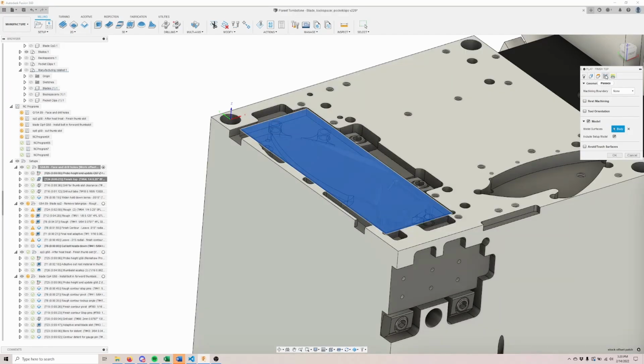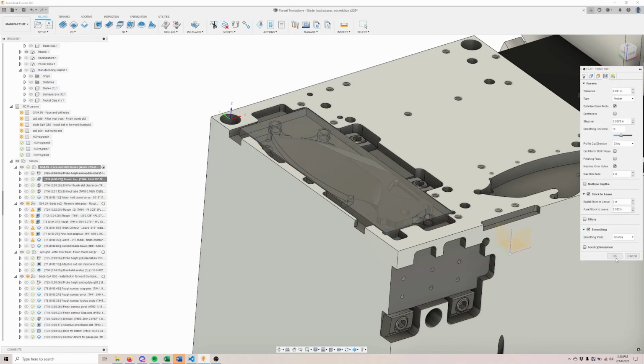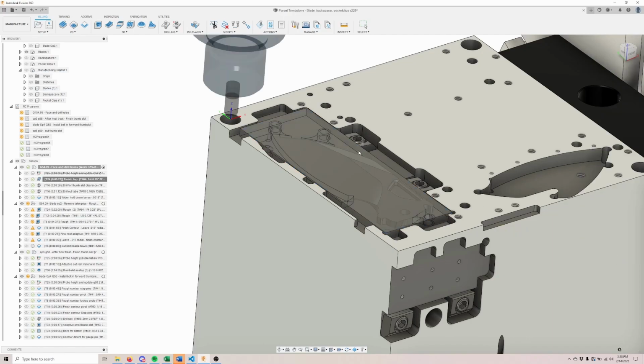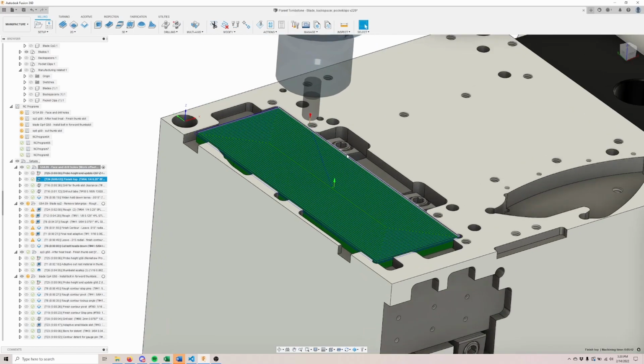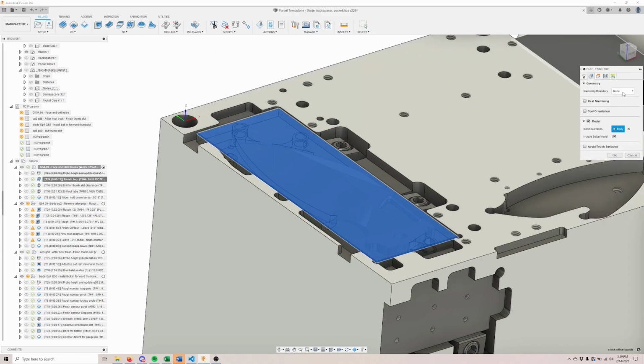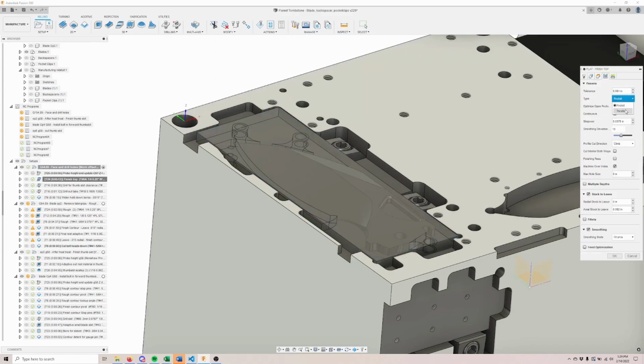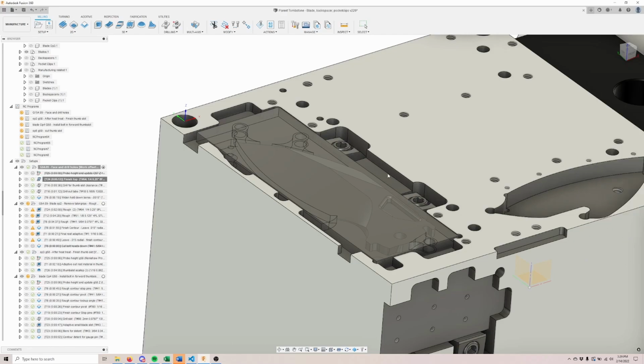But anyways, the reason I'm using a flat toolpath as opposed to a facing toolpath is because I was using flat and using the pocket before, just because this is stainless. It's annealed and it's pretty soft, but still it's better for the cutter, I guess, to do this engaged all the way. But I found that when the cutter comes in and does its final pass, it's rubbing on these last 2 passes. There's no material left, but the cutter is still actually touching the part, which is not really great in stainless, and it dulls the cutter pretty quick.